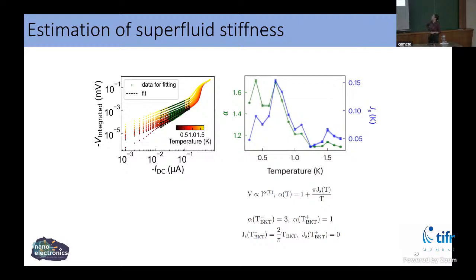Now, what we did was we measured different IV curves at different temperatures in order to get a handle on this alpha. And usually in this field, people did this analysis at a current closer to the critical current, where this nonlinearity mainly occurs because your Cooper pairs have started to depair, because you're sending too much current through it. But the essence of the BKT physics actually happens at a current value which is about one order lower than this critical current. And so we carefully did this analysis at lower values of current. And what we got here is these values of alpha for different temperatures.